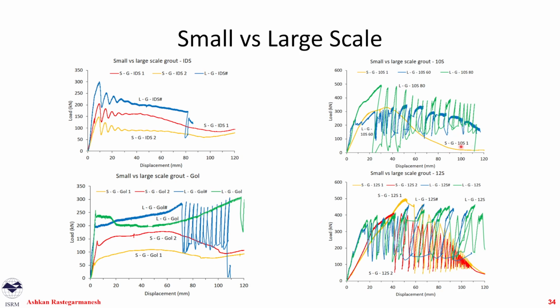We see that, for example, in 10S cable, our larger scale test and smaller scale test tend to match at the 60 Newton meter value of the torque, and in 12S, it is basically similar to the normal test that we did, which was around 80 Newton meter. This is a little bit confusing, because our larger scale test had 300 millimeter of embedment, but our smaller scale had 150. So you expect that you get twice the load. But in reality, you see that different cables are behaving differently.